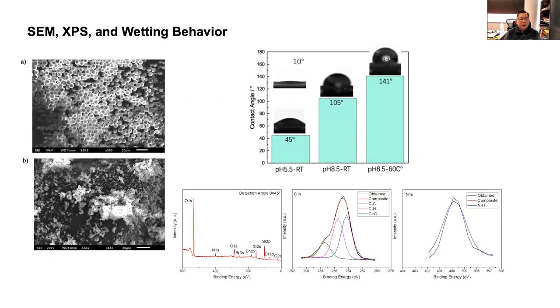Spheres of silica or glass. We then pack them in a column and then introduce the hyperbranched polymer, resulting in a core-shell modified particle. Using XPS, we prove the composition, but also the LCST behavior as well as the pH response.